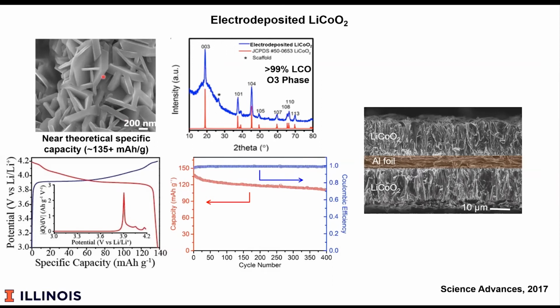Depending on how we grow it, this was intentionally grown to show large crystallites, but one can see that one has large single crystals. These planes here are actually the 003 planes. They do not have fast electron or ion transport. The edges exposed here are 104 and 110 planes. Those planes are open to lithium ion migration. And also the fast electrical conductivity is along the directions of those planes. And so this crystallographic orientation is important. And I will skip over a lot of the details, but this little bump here is a sign of a high quality material.